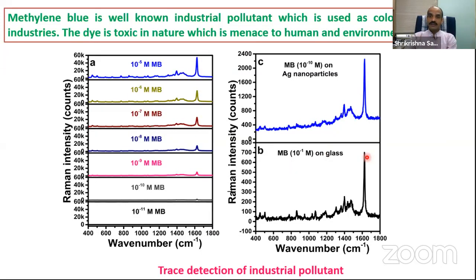If on the other hand, even though the concentration of methylene blue is 10 to minus 10 molar, I can get the intensity of more than 2000. So it is like 3 times higher, even though the concentration is 10 to the 9 times lower. So I can measure ppb, parts per billion, 10 to minus 9, or even 10 to minus 12 molar of methylene blue with this kind of SERS.